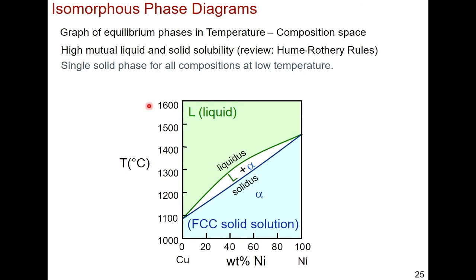So you can go from 0 to 100 weight% of nickel in the copper matrix, and at whatever composition you're at of nickel and copper, in this blue region right here, it's going to be one solid phase, okay? One phase. It's going to be what's called the alpha phase. So you'll see this time and time again, right? With the iron, alpha iron is BCC. But here, this alpha phase, it's now FCC. So alpha is not always one particular crystal structure. We call everything alpha because alpha is A, and we start our alphabet that way, okay? So if we have to start naming things like phases, we just start with the beginning of the alphabet.